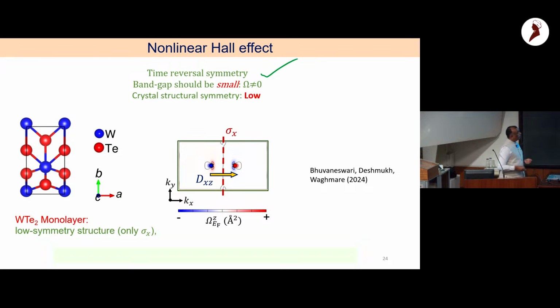So the nonlinear Hall effect says that you can still have time reversal symmetry and see this effect. But unfortunately, the band gap of the material has to be small to get non-trivial Berry curvature. And lastly, the crystal symmetry has to be low. So although it is more common than the anomalous Hall effect, it is still restrictive in that sense. So this is where we started our work.